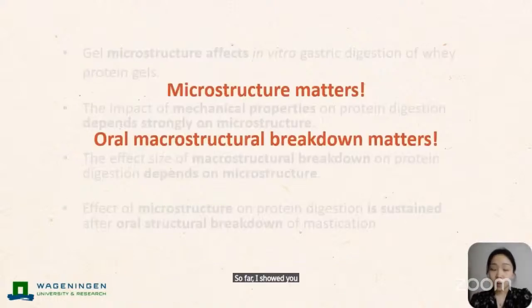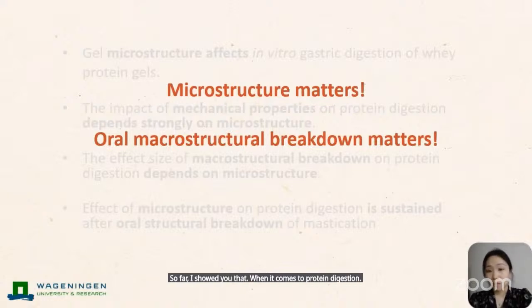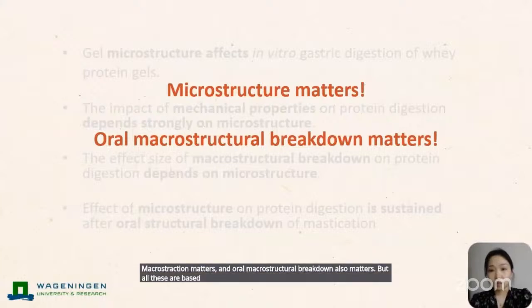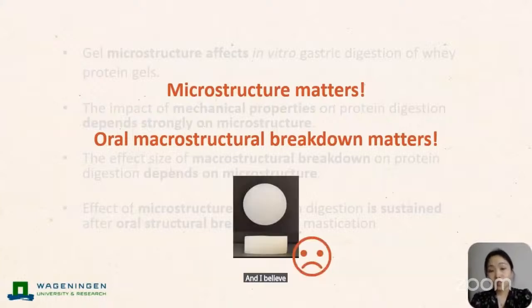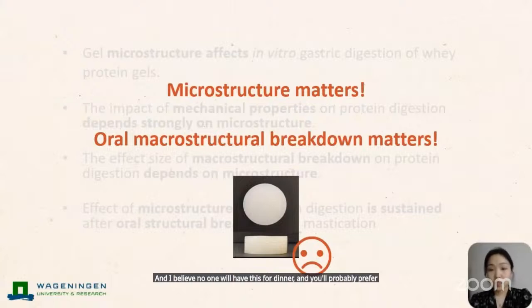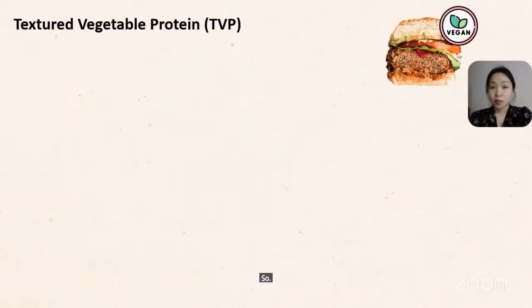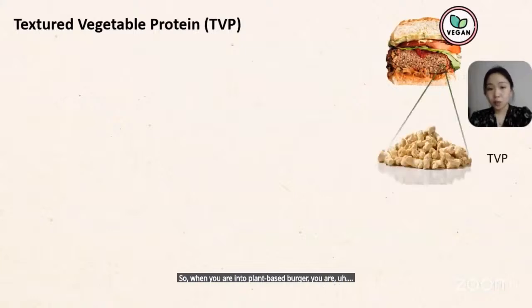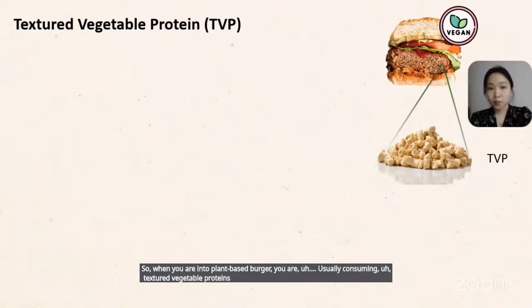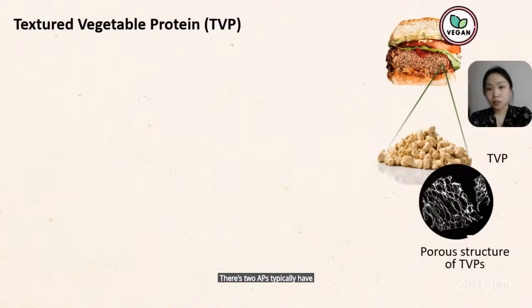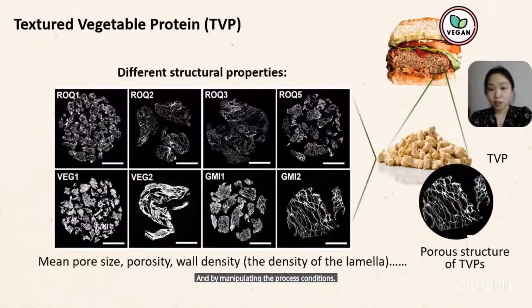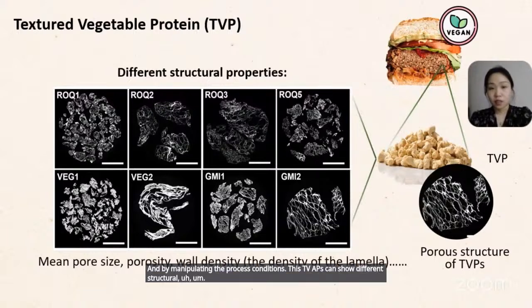So far, I showed you that when it comes to protein digestion, microstructure matters and oral macrostructural breakdown also matters, but all these are based on studies on model gels. And I believe no one will have this for dinner, and you probably prefer a plant-based burger. So when you are eating a plant-based burger, you are usually consuming textured vegetable proteins, or TVPs. These TVPs typically have a porous structure to mimic the texture of meat. And by manipulating the process conditions, these TVPs can show different porous structures, and these structures can differ in many properties such as pore size, porosity, and wall density.